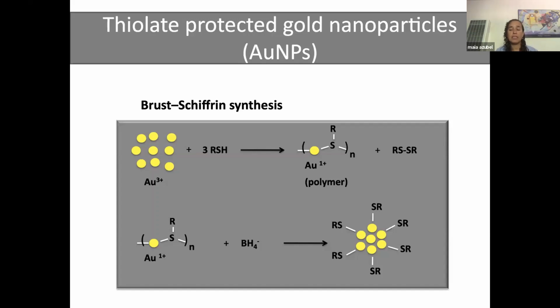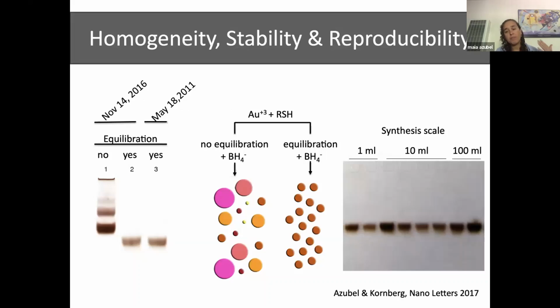There are a lot of properties that are related to the core of the particle, but you will see that when you prepare these particles with the aim to bind them to protein, whichever thiol you use is very important. So again, I'm a brand new postdoc in the lab of Roger Kornberg, where all of a sudden doing crystallography of gold nanoparticles seems very interesting, but we have a little bit of a problem with gold 102. The problem with gold 102 is that the synthesis was not very reproducible, and when we tried to attach to protein, it worked, but we wasted a lot of gold.